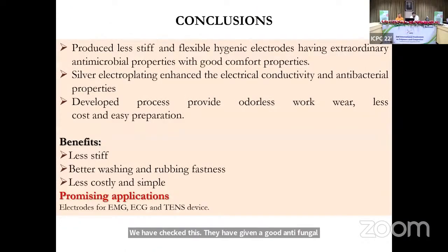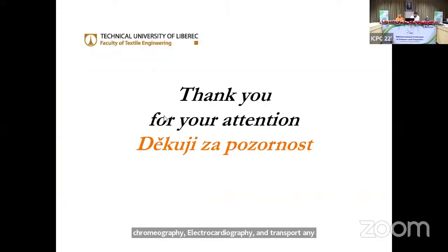We can conclude that we have produced less stiff, flexible, hygienic electrodes having extraordinary antibacterial properties with good comfort properties. Silver electroplating was used to enhance the electrical conductivity and to give the antipathogenic properties. So we have developed odorless workwear with less cost and easy preparation. The benefits of these electrodes are that they are less stiff, have better washing and rubbing fastness, and are less costly and simple. The promising applications of these electrodes are in medical devices like electromyography, electrocardiography, and transcutaneous electrical nerve stimulation devices. Thank you.